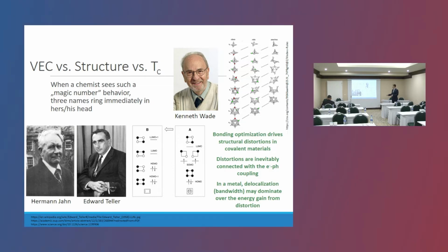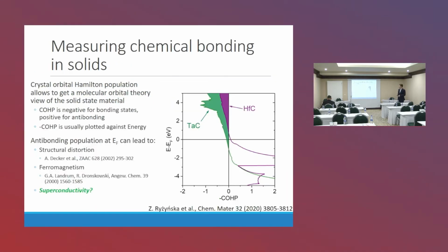The other two names are Jahn and Teller, because you're probably all familiar with the Jahn-Teller effect. The Jahn-Teller effect is a phenomenon in which there is a large electron-phonon coupling coming from some discrete electronic configurations in covalent systems, at which electron movement is associated with some distortion, a phonon mode, which leads to the distortion. In a metal, that distortion can be kind of arrested because the delocalization energy, the bandwidth energy scale, may dominate the energy gain from distortion. Okay? So in a metallic system, the Jahn-Teller effect can be kind of non-static and it will form some kind of soft modes but will not result in complete distortion.